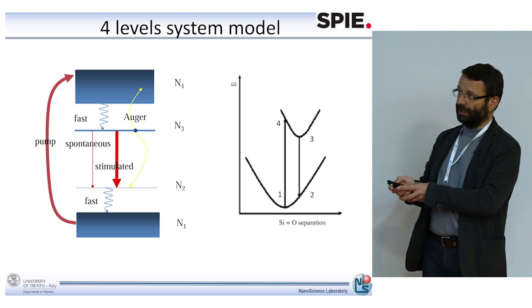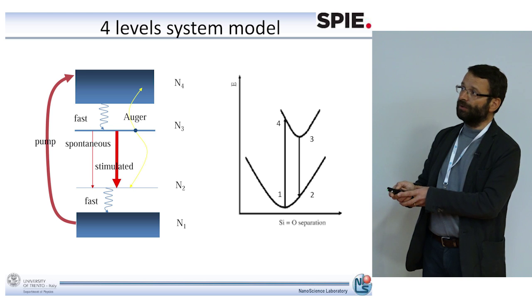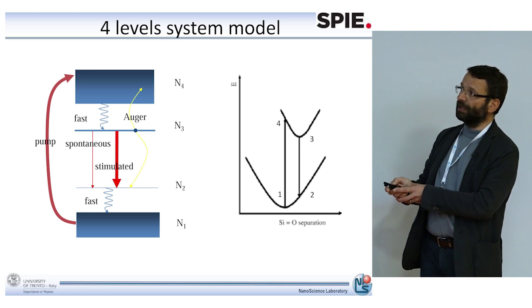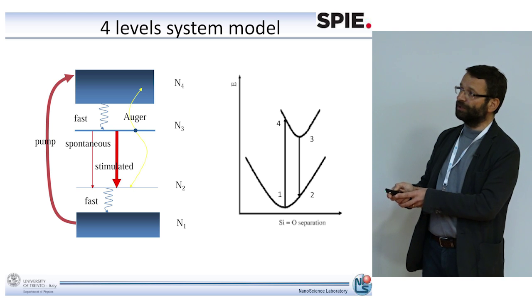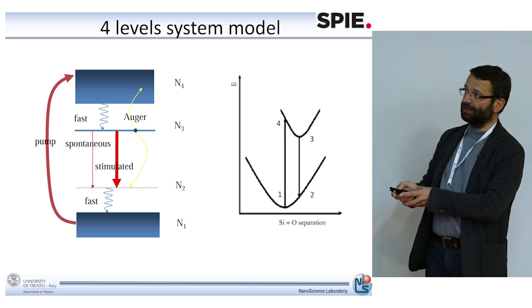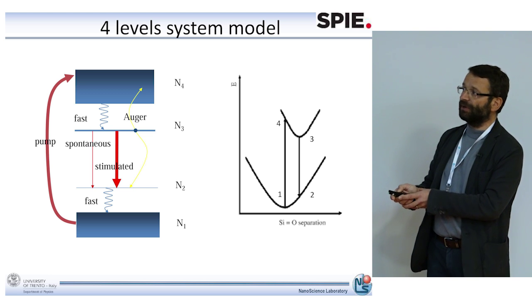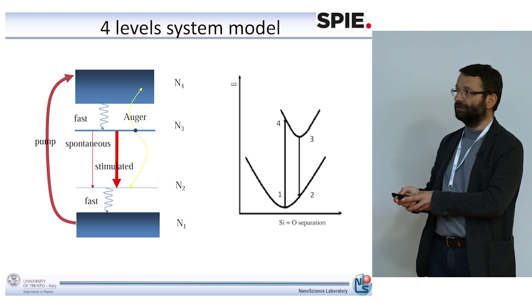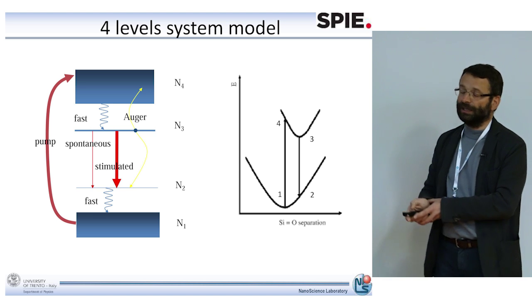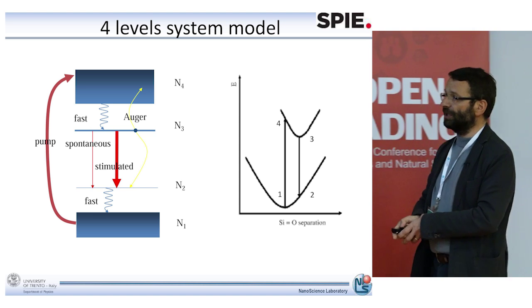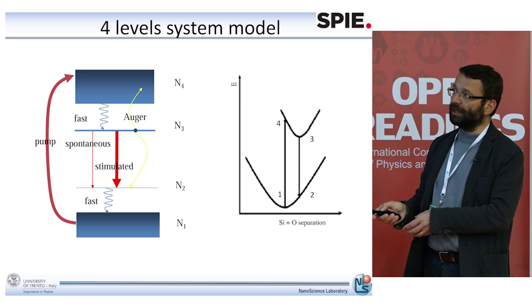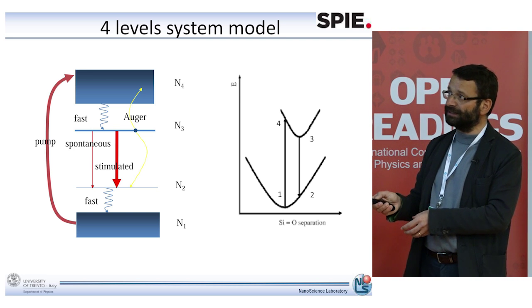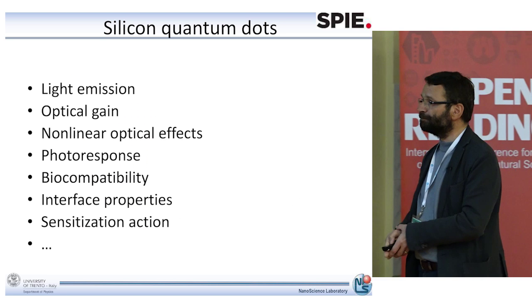Then you have an interdefect relaxation from 4 to 3. And now you are in this level here. And then you get recombination between level 3 and 2. You get recombination, that is the stimulated recombination, between level 3 and 2, and then you have the relaxation of the defect back to the ground state, so you get the relaxation back to this state here. And this explains the fact that the absorption is spectrally separated from the gain.